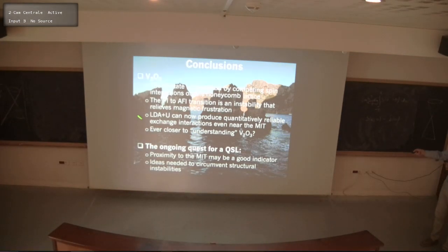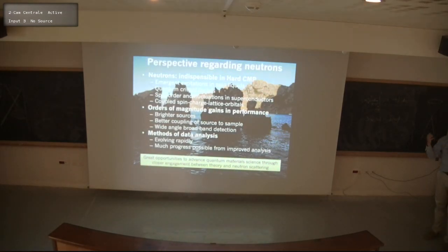That's what I basically was just mentioning about V2O3, and then to connect it to what I was saying about the spin liquids, we think that that's actually a very good place to look for spin liquids. We in fact should be looking close to the Mott transition, and there are ways that you can argue for that as well, because proximity to the Mott transition tends to induce longer range interactions, because you've got the fluctuating charge allowing you to extend the range of the interactions, and that may in fact help to build fluctuations into the spin system.